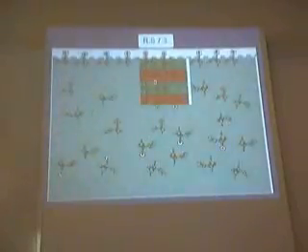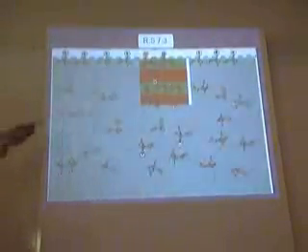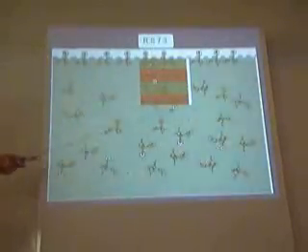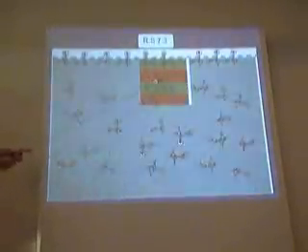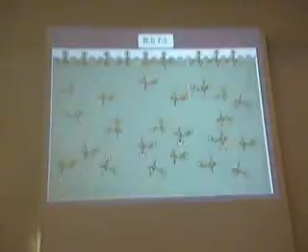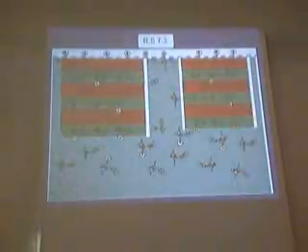let's say we can grow these crystals, they pick up. These ones are much smaller crystals because we have fewer green molecules at the air-water interface, but we have more of the red, and at a certain concentration, this red can prevent these small crystals from growing. What we observe is that they don't grow, and we actually grow crystals of only one enantiomer.